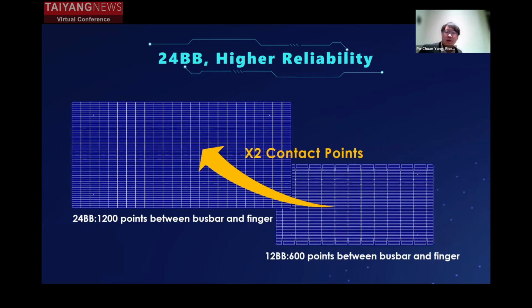So here, talking about 24 busbar design, like I mentioned, in cell level, this is 0 busbar design, but since we are a module maker and we just provide the module to our customer, we will not focus on how many busbar we are using on cell level. But finally, this is 24 busbar design in module level. So if we have more busbar, that means conduction distance will be shorter, reducing the current density and also power loss, and increasing the cell tolerance to microcracks and finger breakage. And the most important thing is busbar and finger contact points increase 2 times. That means the module reliability will be better compared to 12 busbar design.